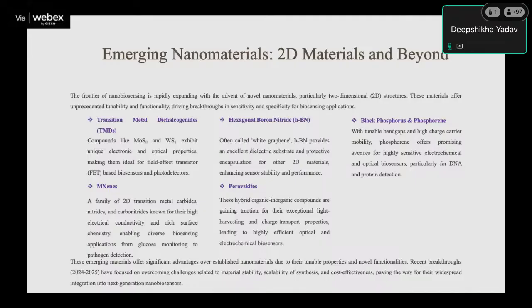The common structure is like a sandwich, where the central plane of molybdenum atoms is sandwiched between two hexagonal layers of sulfur atoms, and the sulfur atoms are bonded to the molybdenum atoms by strong covalent bonds. However, these layers are bonded to each other by non-covalent interactions, which are van der Waals interactions. So they can be easily exfoliated into 2D sheets, which imparts their unique catalytic properties in biosensors. The basal plane of these 2D sheets is usually inert. However, the edges are highly reactive, and they are commonly known as the active edge sites, which impart their catalytic properties.